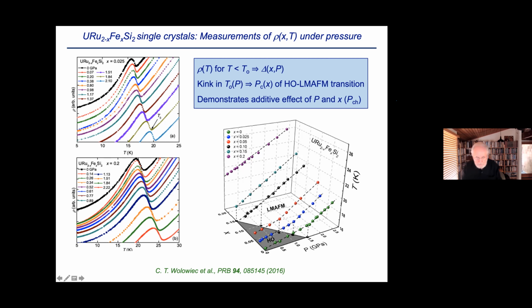So basically, this says that in tuning the hidden order phase to drive it into the antiferromagnetic phase, either by pressure or by substitution of iron, these two contributions are additive. And so if you put a little bit of pressure on it, or if you put a little bit of iron in it, then you need less pressure to go through the transition. And so these two mechanisms are additive.